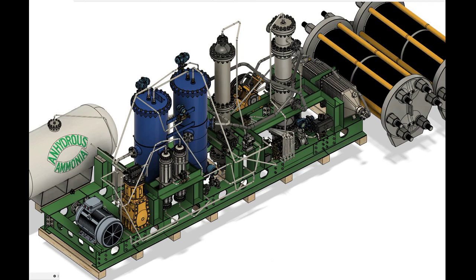This alloy is used for the converter wall construction, and while this is still a very high-strength alloy, ammonia converters are rarely made out of high-cost nickel and chromium alloys, such as Inconel. The ultimate tensile strength of ASME SA542, grade B, is approximately 860 MPa, while the yield strength is 585 MPa, but this strength falls considerably at its 450 to 500 Celsius operating temperature, while stainless steel or Inconel, thanks to its nickel content, retains most of its room temperature strength at 500 Celsius.